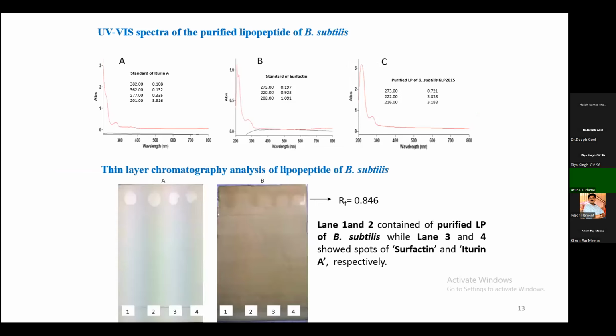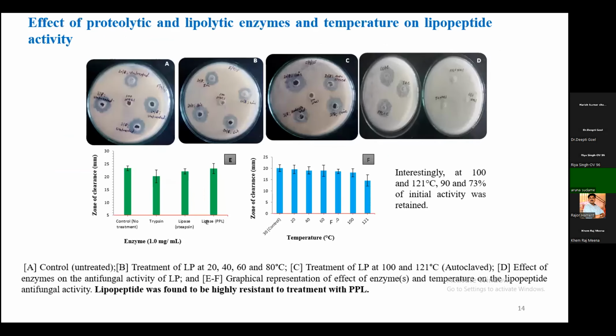In the UV-visible spectrophotometer, we used iturin and surfactin as standards. In the upper graph we can see that the purified lipopeptide matches the surfactin. In the thin layer chromatography, the white spot shows the presence of lipid, and the green spot presents amino acid, which shows the compound is a lipopeptide. This lipopeptide is very stable at high temperature. It was active even after autoclaving at 100 degrees centigrade, even 120 degrees centigrade.